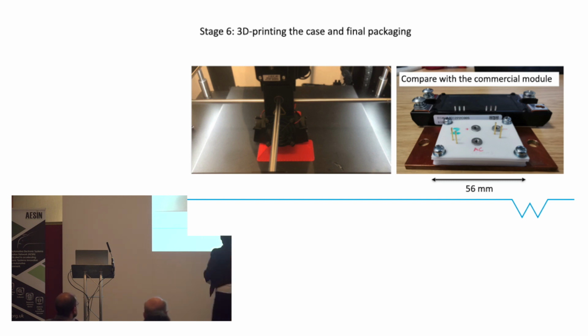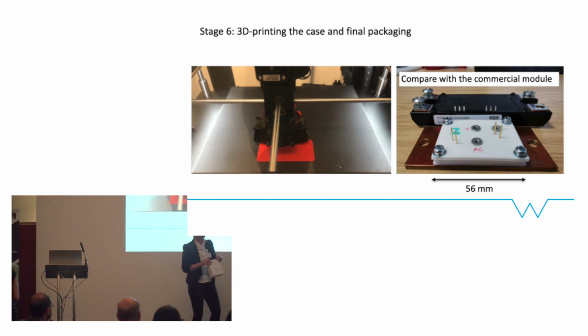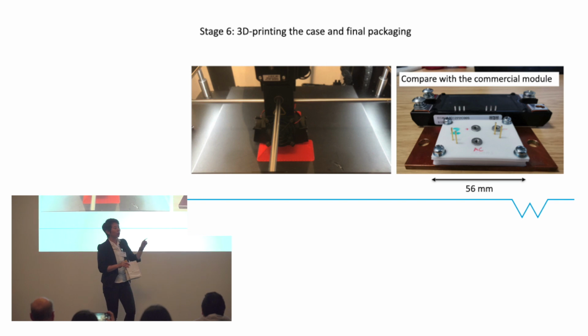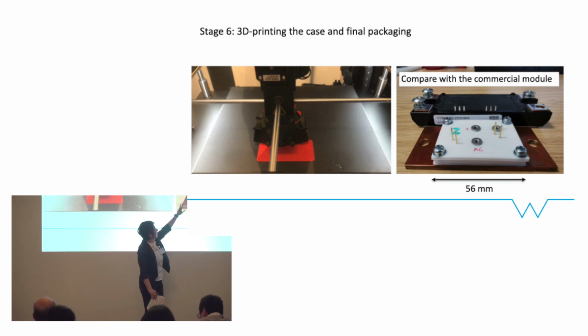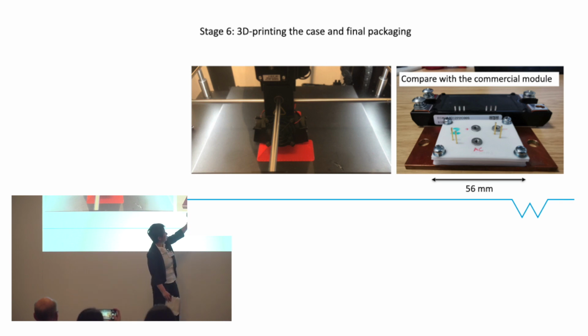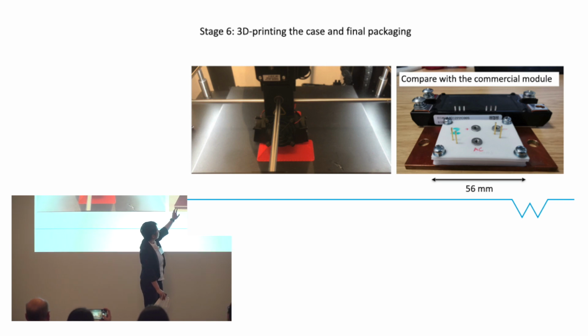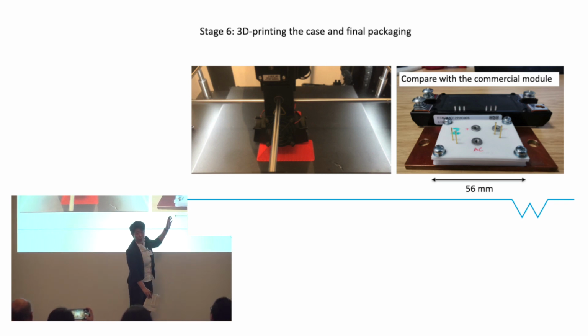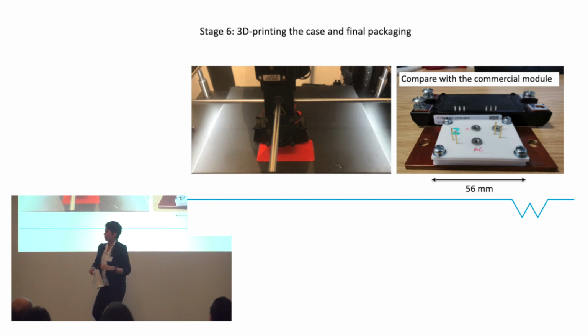So for this module, the voltage rating is 1.2 kilovolts. The current rating is 100 ampere. So the power rating is 120 kilowatts. This is a comparison between a commercial model with similar power rating. You can see we reduced the size further. And for the base plate, the size can be reduced as well. This one is designed especially to fit on our fans in our laboratory, which we already have. So we increased the size a little bit, but you can reduce the size of the base plate further.